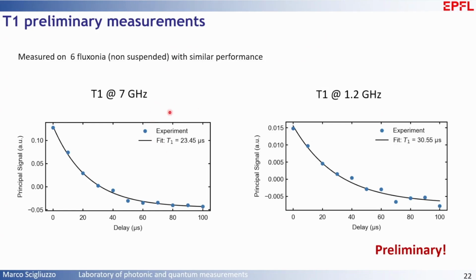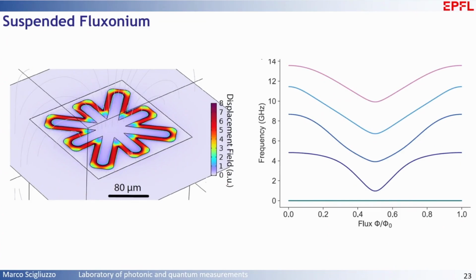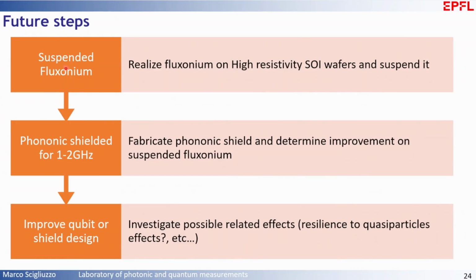And the lifetime of this fluxonium, which I remind you is non-suspended, just a fluxonium on normal silicon, is also quite decent. So in the next step, indeed, we are designing a fluxonium that is suspended on the silicon membrane that is phononically shielded, as I showed before. But you can see that now this is only a 150 or 200 micrometer by 200 micrometer release gap when you need to release it. So in the following step, indeed, we'll realize the design that I showed.